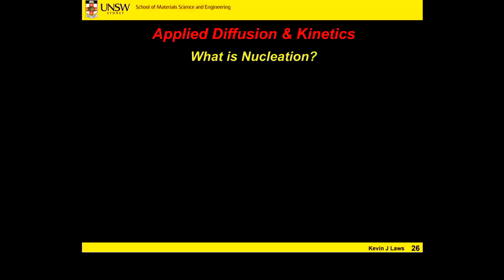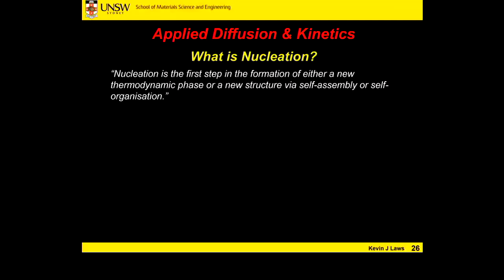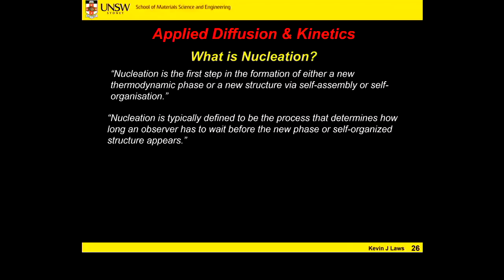This doesn't happen everywhere instantly. It will often happen at a specific site because that site will be of lower activation energy than another. Okay? So nucleation is the first step in the formation of either a new thermodynamic phase or a new structure via self-assembly or self-organisation. Nucleation is typically defined to be the process that determines how long an observer has to wait before the new phase or self-organised structure appears.